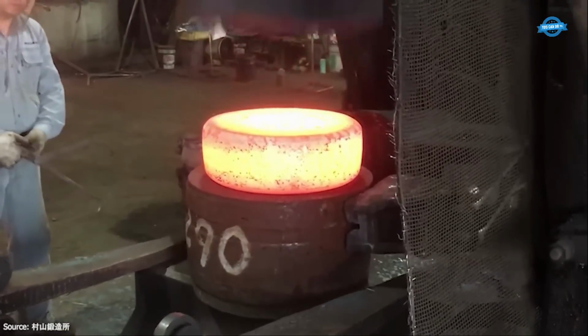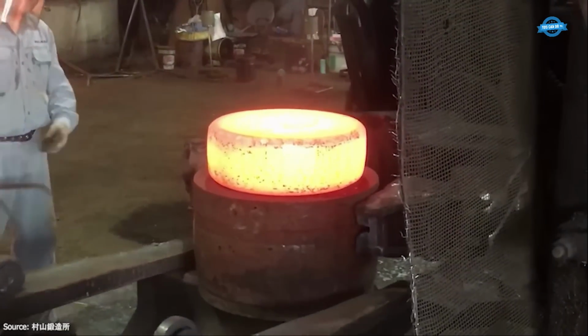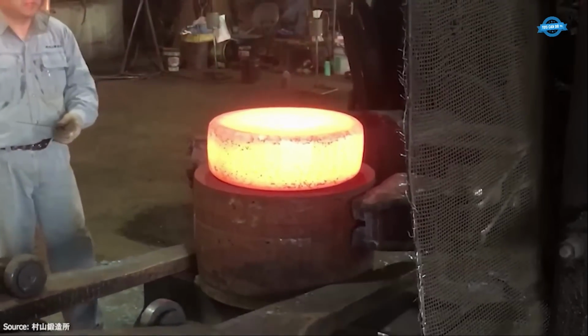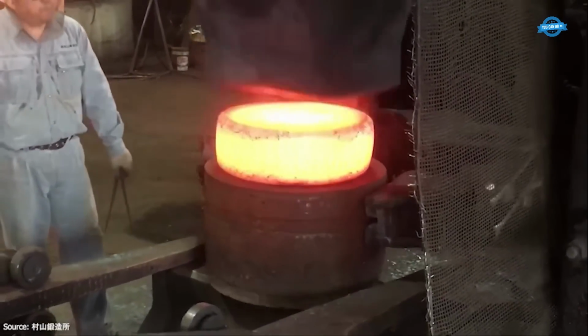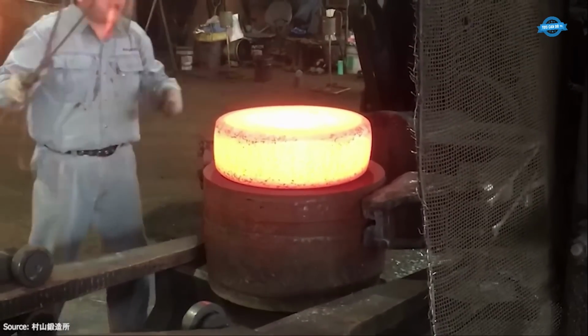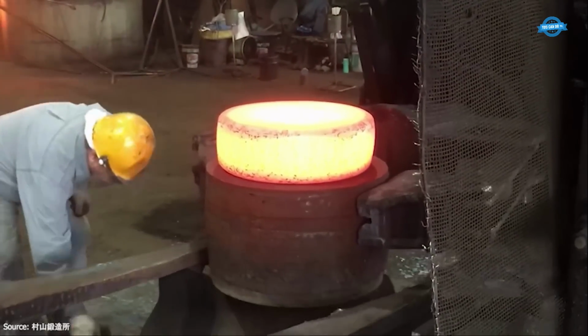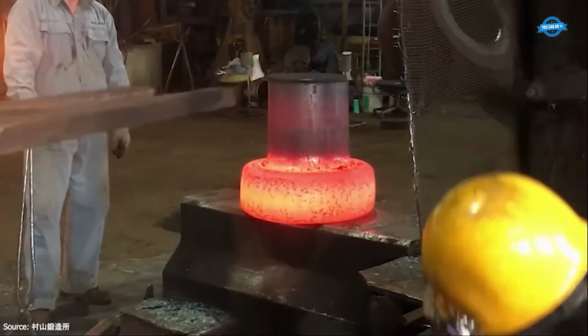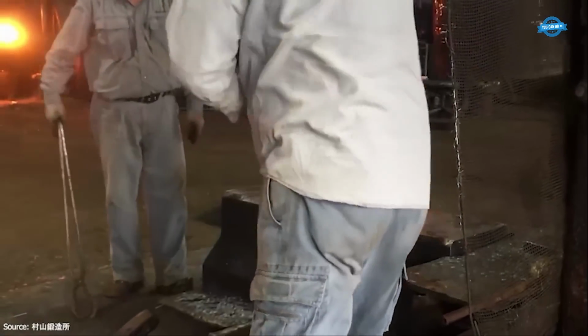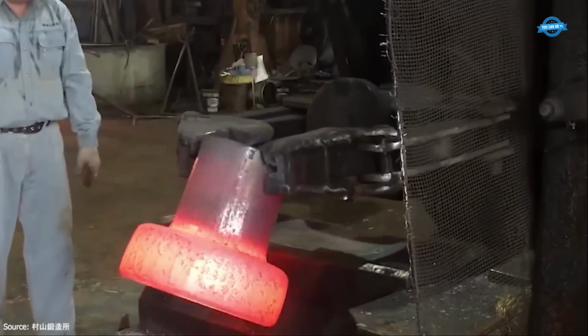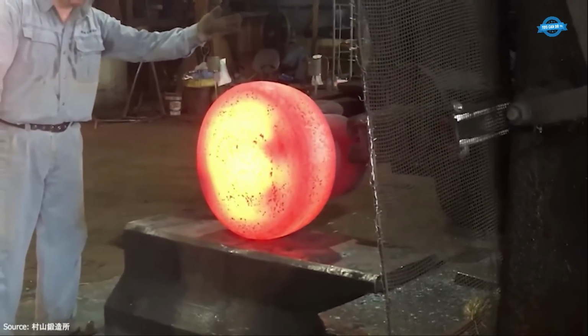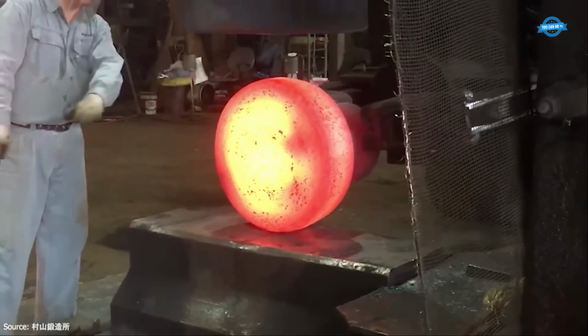The billet is removed from the furnace. Surface scale, which forms as a result of the billet's exposure to oxygen at high temperatures, is removed. This descaling is critical. Leftover scale can cause surface flaws or inclusions during forging. Descaling is performed using a combination of high-pressure air jets and mechanical scale breakers to achieve a clean, defect-free surface.